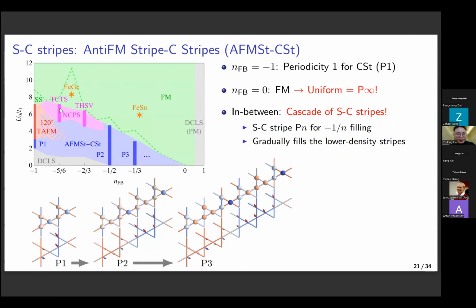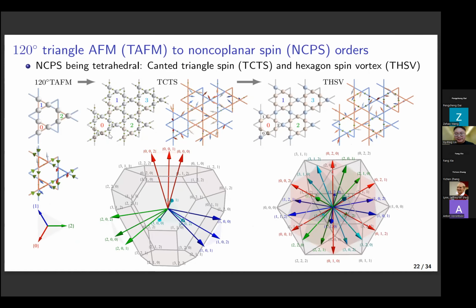And if we now go a little bit higher into -2/3 filling, that is, 2/3 filling between -1 and -1/2, we will see that because the charge density is increased, the higher density will now be the center hexagon of 3 nearest neighbor triangles. And if we look at the magnetic order within this hexagon, we will see that the 6 magnetic orders will form a coplanar order. And because they are winding around the plane, we call it the hexagon spin vortex. And now if we compare the magnetic order on 4 nearest neighbor hexagons, we will find that the normal vectors of their planes will be tetrahedral to each other. So we call it the tetrahedral hexagon spin vortex order.